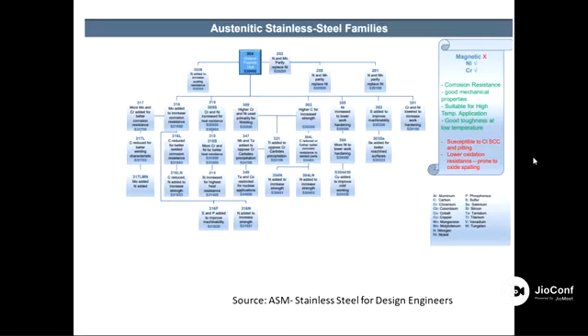Because when we have to put these steels in an environment where there are chromium carbide or sensitization issues, we use 321 grade, 347 grade. So there are very specific applications for this stainless steel family. Overall, austenitic stainless steels have good corrosion resistance and are suitable for high temperature. But the drawback is they are susceptible to chloride stress corrosion cracking. In a chloride, saline environment, they suffer from stress corrosion cracking and pitting corrosion issues, and they are not good for high oxidation, not for high temperature applications above 350 degrees Celsius, because they are prone to oxide spalling.